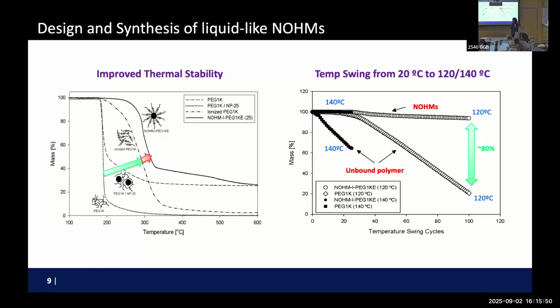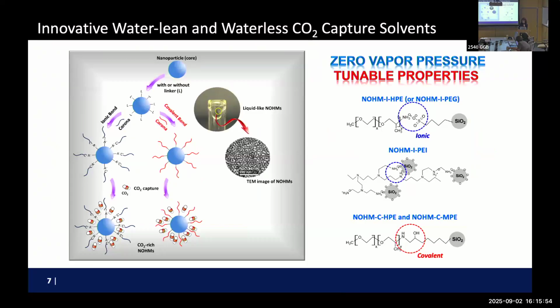What we found out was, in fact, those waters were stuck in between polymer chains. This is drawn with CO2, but water was in between polymer chains. So what happened was CO2 can penetrate through that layer easily and get to the amine functional groups. At the same time, oxygen did not like the water, it was staying outside. And because of that, we were able to protect all these amine functional groups.